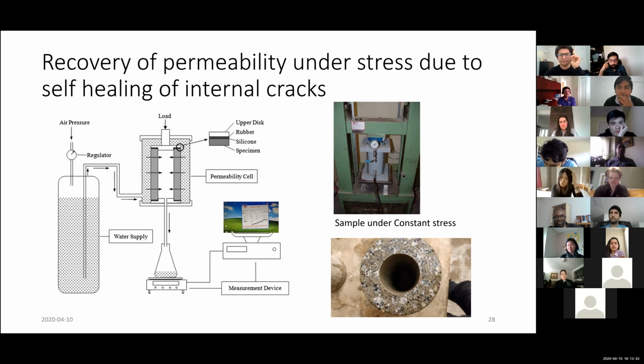Anupam, I saw in some of your slides that you sometimes use a fan to cure the samples. No, it's not to cure, it's basically to subject them to a constant flow. The fan was a rotating fan, and I spread the samples around at a certain distance. It ran for 24 or 48 hours, putting all those samples under a constant flow of air. But if we do that at the very early age of concrete, it affects the hydration and evaporates some of the water from inside and damages the sample.